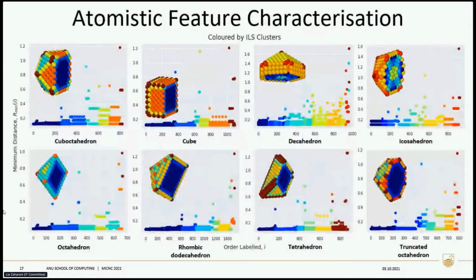We now look at the clusters identified using ILS and the peak finding algorithm. You can see that the algorithm works equally well across different shapes, and the resulting clusters make a lot of sense from the catalysis point of view. The clusters mostly correspond to the atomistic patterns that we are familiar with, like edges, corners, and different faces. It is also interesting to see that the method is capable of distinguishing bulk atoms, like twin planes and the subsurfaces.